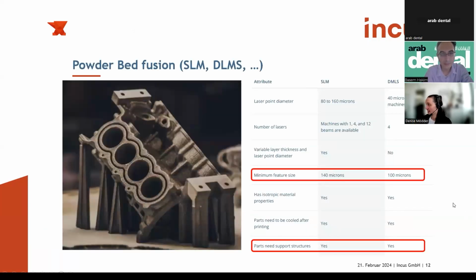Just to give an example of the comparison with the powder bed technologies, not including binder jetting here, but everything that is related to powder bed fusion, selective laser melting, or selective metal sintering, we only can get feature sizes of 100 to 140 micron. We need support structures for those parts, and we have a really rough surface here.